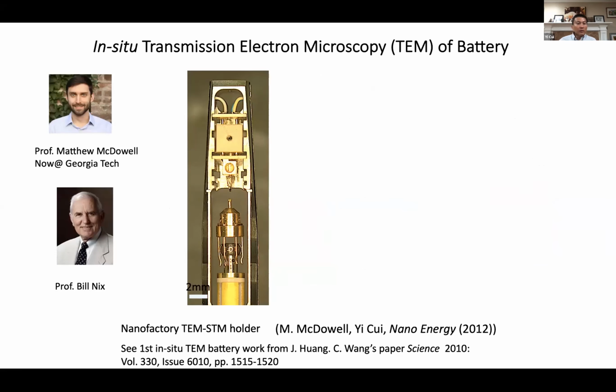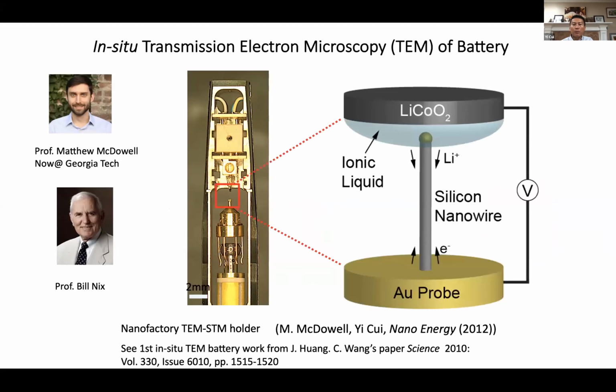And we adopted a tool very early on, about a decade ago, which is to use in-situ TEM. So I keep emphasizing the tool. That's important for us to understand what's happening. So with this TEM holder, there's a piezoelectric control. We can mount the nanostructure such as a nanowire to the tip and apply a voltage right there, forming this nanoscale battery. You can drive lithium coming in, electrons coming in, lithium diffusion, and start to react with silicon to look at the lithium reaction process with the materials in real time.